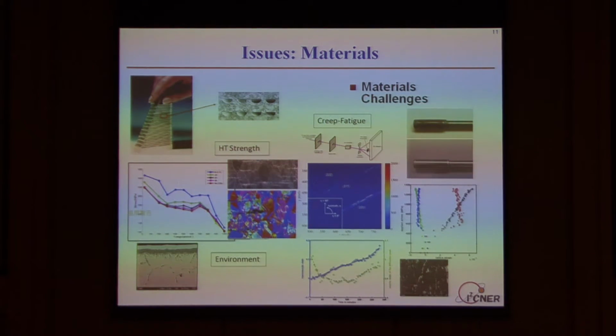So there are lots of materials issues, and I've done one slide as a snapshot of all of these. This is a typical heat exchanger in this system, which is the primary materials issue for very high temperature issues. And so there are lots of strength problems. This actually is yield strength versus temperature. And you can see at high temperature, maybe you can't see, by the time you get up to 900 C, the strengths are a fraction of what they are even at moderate temperatures up to 600 C. There are a lot of issues with corrosion in these materials. There are a lot of issues with materials fabrication and internal degradation under loading conditions.